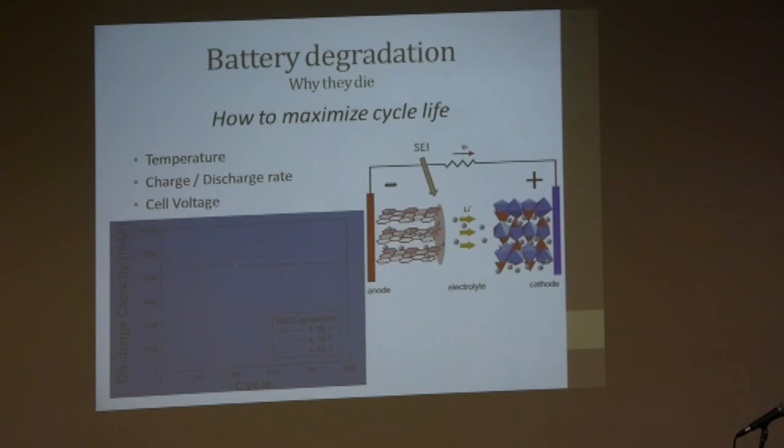Now, that process is almost the same as what happens inside a battery, but you don't want that to happen. But if you discharge them too far, that can happen, and you can get little metal hairs in there, and they create internal short circuits. And that means the self-discharge goes up. Internal resistance also deteriorates.